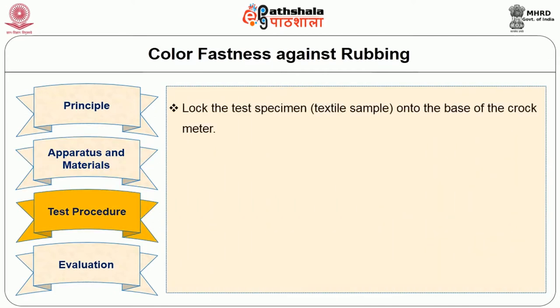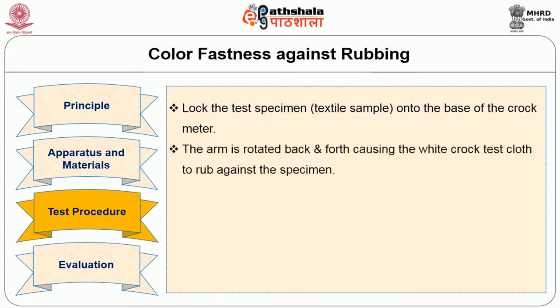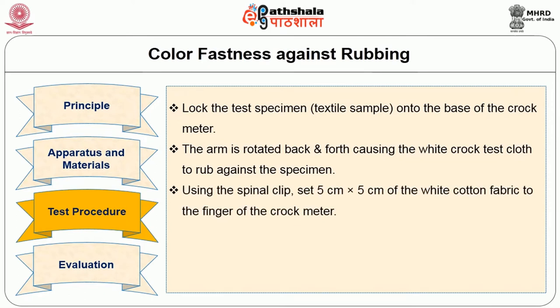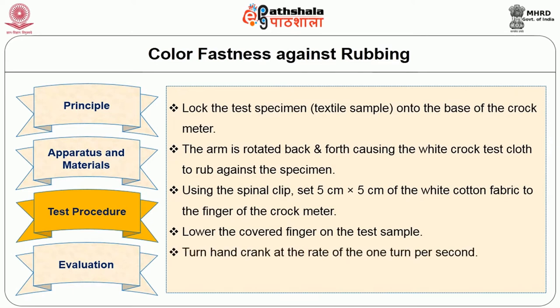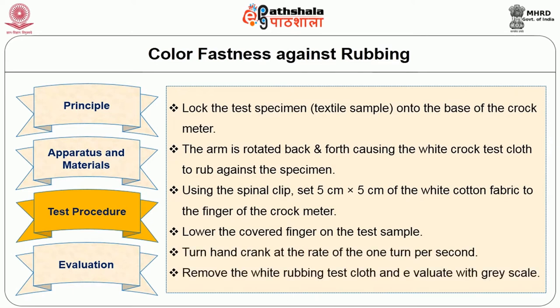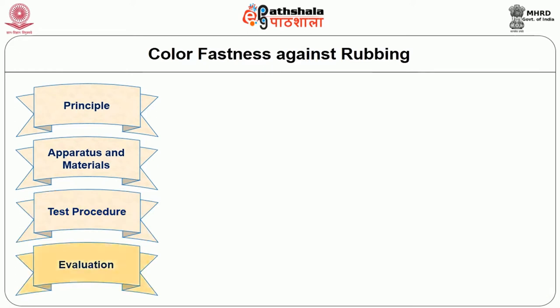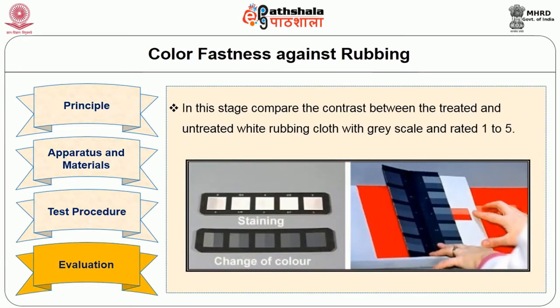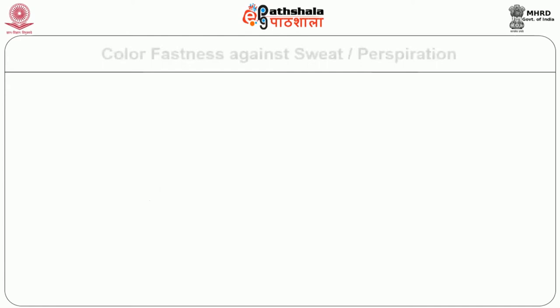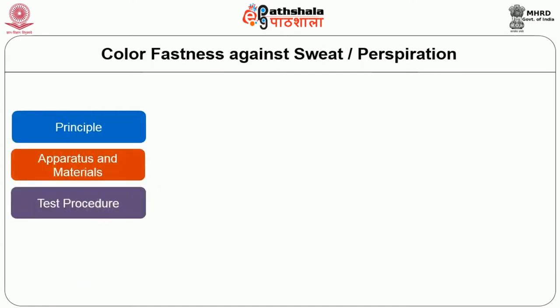Test procedure: lock the test specimen onto the base of the crockmeter. The arm is rotated back and forth, causing the white crock test cloth to rub against the dyed fabric. Using a spiral clip, attach a 5 cm by 5 cm piece of white cotton fabric to the finger of the crockmeter. Lower the covered finger onto the test sample. Turn the hand crank at the rate of 1 turn per second. Remove the white rubbing test cloth and evaluate using the grayscale. In the evaluation stage, compare the contrast between the treated and untreated white rubbing cloth with the grayscale and rate them 1 to 5.